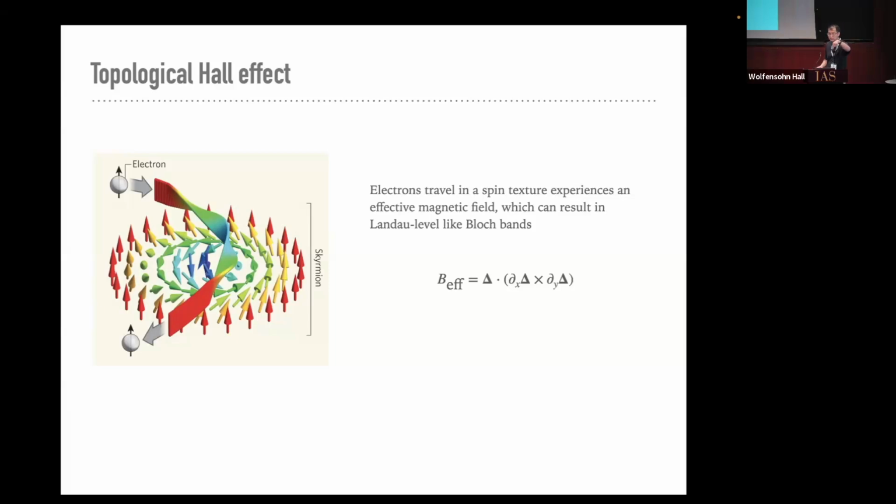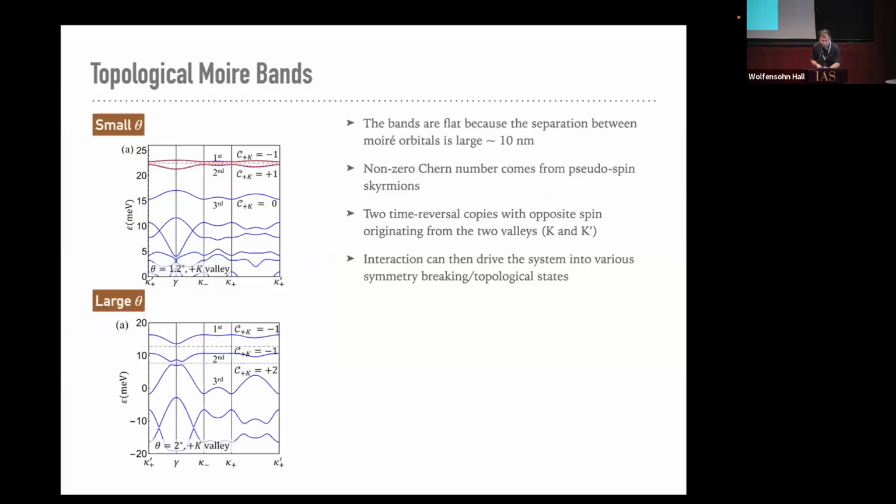Now, if you flip one of the components, then the topological Chern number would have to change. Okay, so with that being said, Alan has done the calculation of the topological band structure. You can see that at a small twist angle, which in their calculation is about 1 degree, you can see those Moiré mini bands. And most importantly, you have the two very flat bands, and they have opposite Chern numbers, -1 and 1. And that's why some people will say that the twisted TMD actually realizes the Kane-Mele model. But I will show you that that's a twist angle dependent statement.